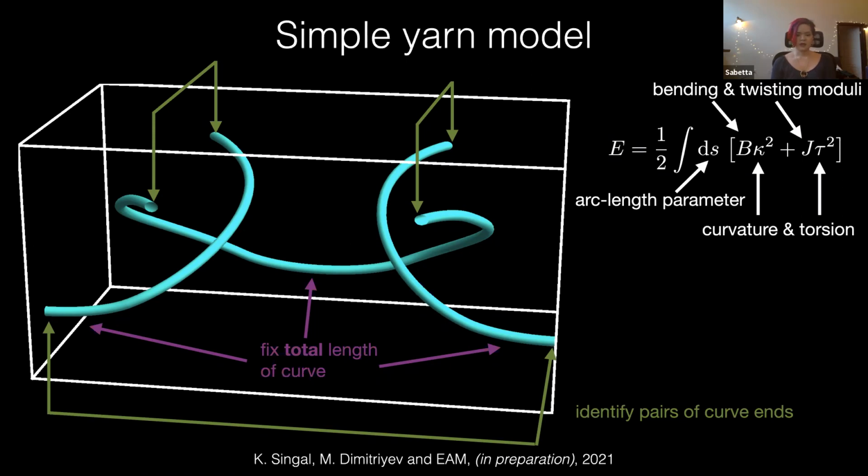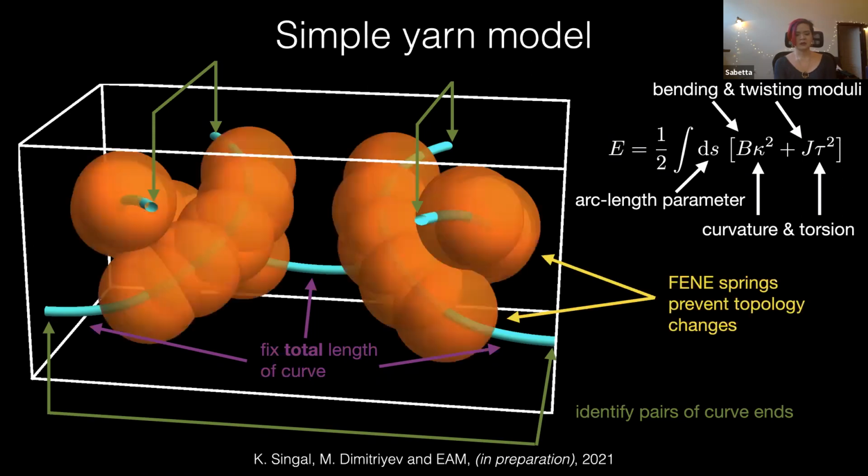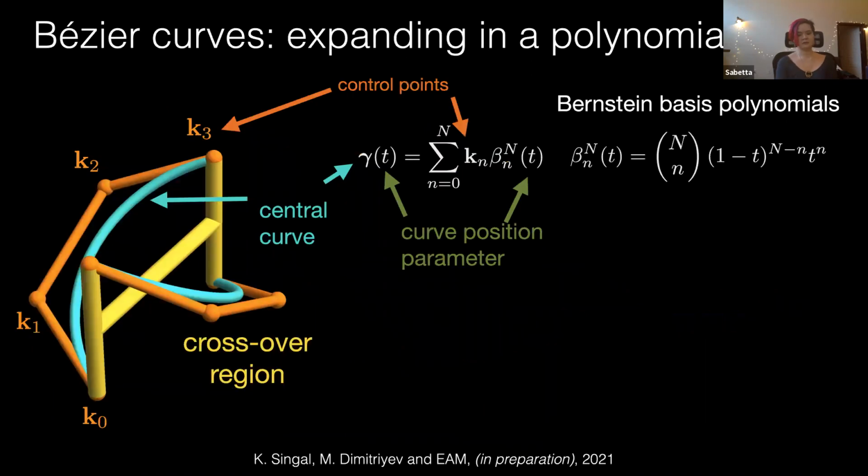Basically after that, he has a yarn-yarn interaction energy. This comes from measurements we do on the yarn itself. So he just feeds in the bending rigidity and the compressibility of the yarn from experiments. And then basically does the same thing that Krishna does by applying forces. Oh, sorry, I forgot to say, let me just go back.